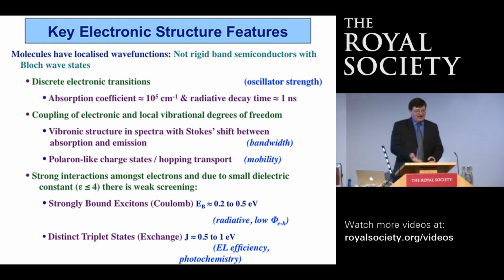Basically, we have to give it a tap, and it has to somehow jump out of the well, and it then drops into another space on the rubber sheet and sinks in again, and we have to knock it back up again. And so, if you like, there's this hopping motion of the charge as it moves across that rubber sheet. And a consequence of that is clearly that it's harder to move that charge around, and so it actually moves more slowly if we want to move it across our material.